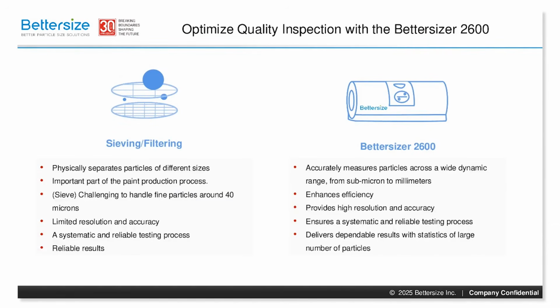As a summary, let's talk about how we can measure particle size to optimize quality inspection. Traditional methods like sieving and filtering have long been an important part of paint production processes. Sieving physically separates particles, which is essential. However, it presents some challenges, especially when dealing with fine particles around 40 microns and below, due to issues like mesh size limitations and particle agglomeration. It can be difficult to handle these fine materials effectively, and the resolution and accuracy of sieving can be limited. While sieving provides a systematic and reliable process, the results themselves can lack the precision needed for modern formulations.